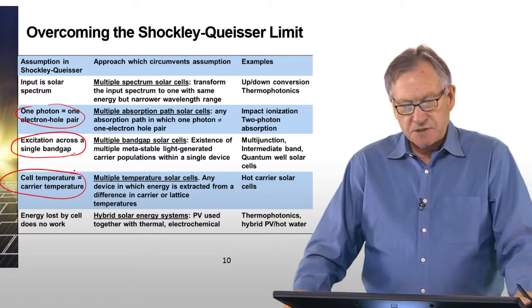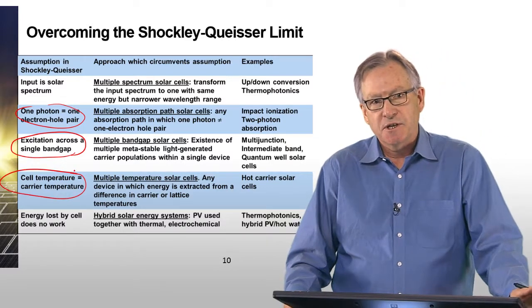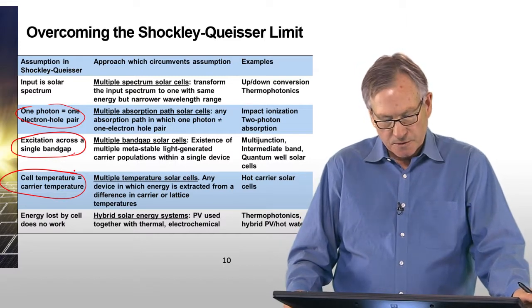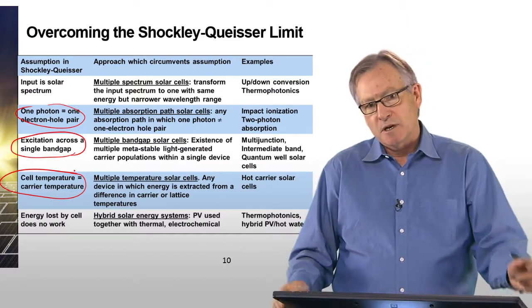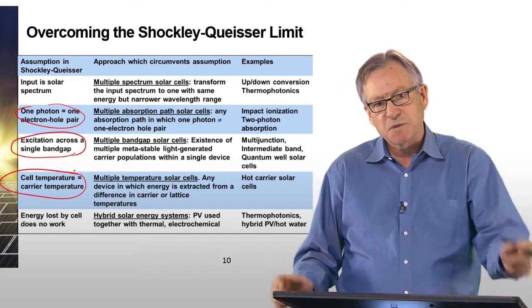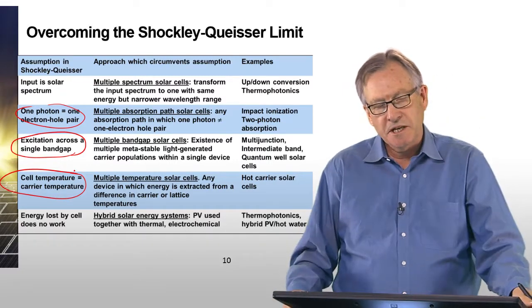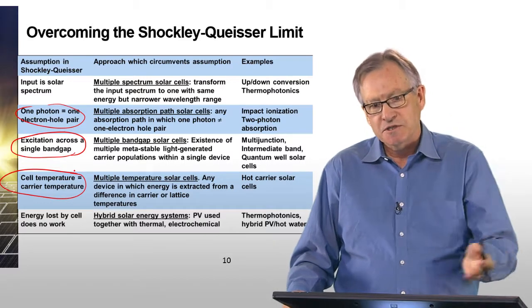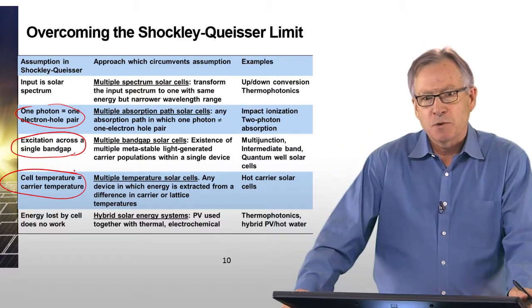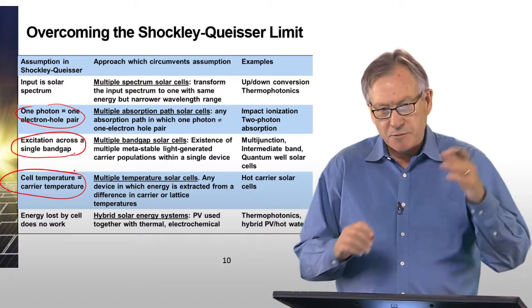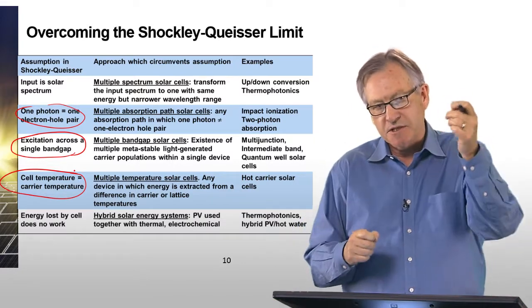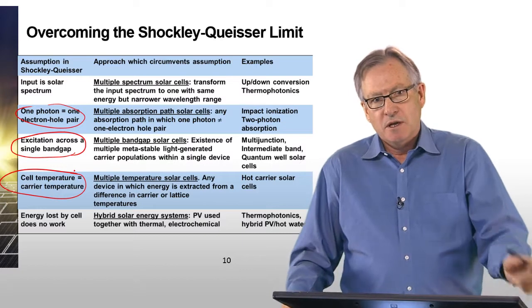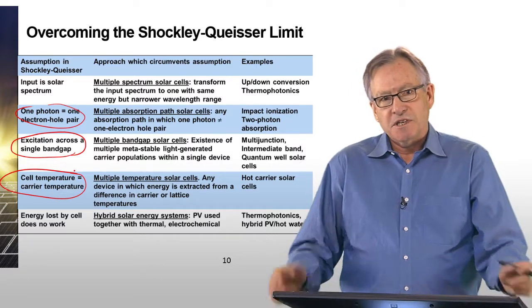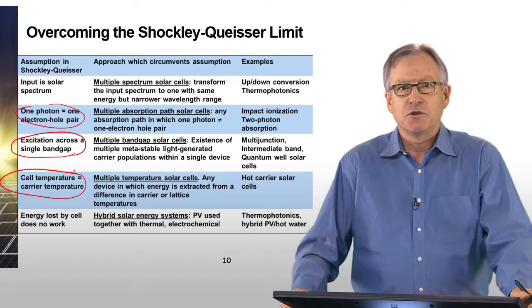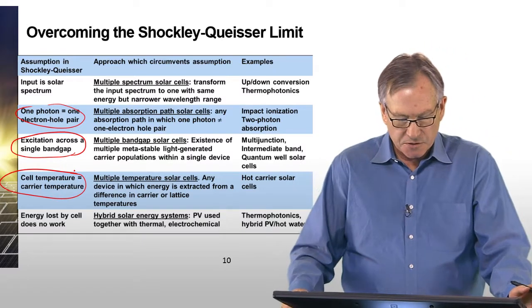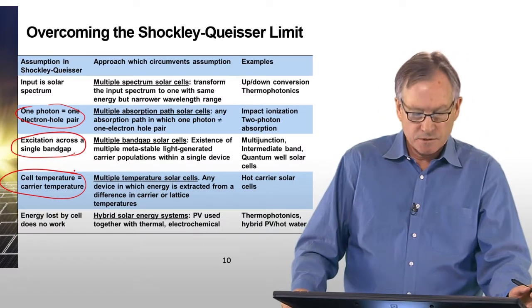There's also the assumption of collecting the electrons at the band edge, in other words, at the temperature of the crystal. But if you could harness the energy of the electrons before they have time to lose their energy to heat, you could also have a high efficiency cell. There are ideas in which, if one could keep the heat energy and the excess energy of the electron within the cell and extract the electrons at high energy rather than at the band edge, then you could also exceed the Shockley-Queisser limit. This is the so-called concept of hot electron solar cells.